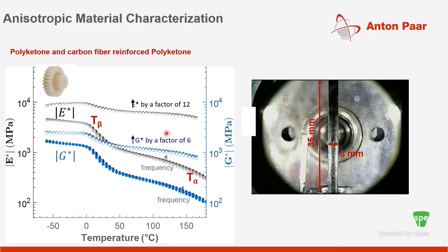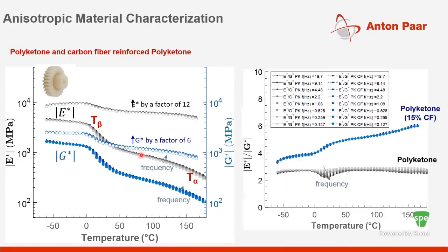Typically, if you take a look at typical polymers, the ratio of E to G is between 2 and 3 - that's the typical range. But if you have anisotropy, these become much higher than 2 to 3, which we canonically know for normal polymers. So now you have a way to measure this E over G, and this ratio is highly temperature dependent.